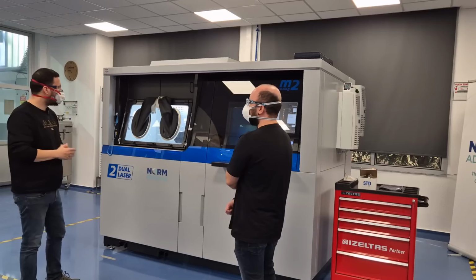Printing goes like this. First, the pieces are divided into slices in that slicing program. While writing each slice, the laser processes along the cross-sectional area of that slice and melts that powder area. Afterwards, the system we call recoater puts new dust on it once again. The laser carefully and meticulously finishes the process by precisely writing the new slice on top and adding it to ensure accuracy.